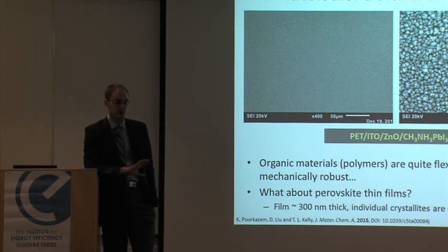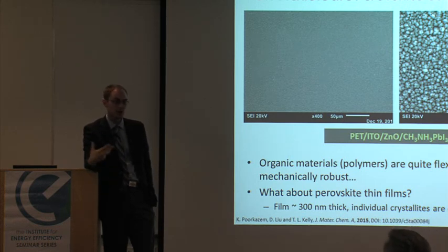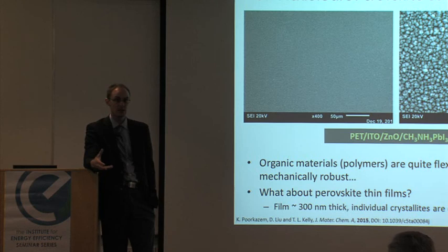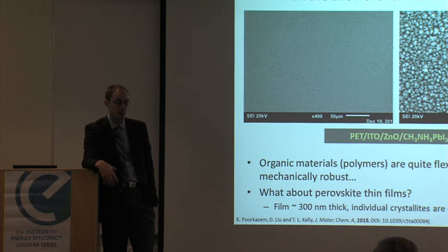So the theoretical work was all single crystal, theoretically sliced and put onto a zinc oxide surface. So it's a very idealistic picture. I think what it does give us is a suggestion that thermodynamically, the idea is not crazy, that you do have enough basicity there to potentially pick off a proton. Of course, with our synthesis, we do this from potassium hydroxide solution in the presence of acetate.